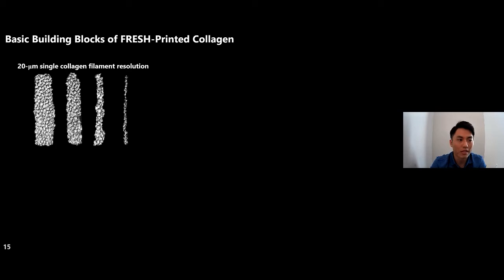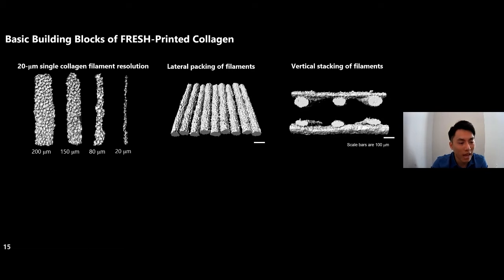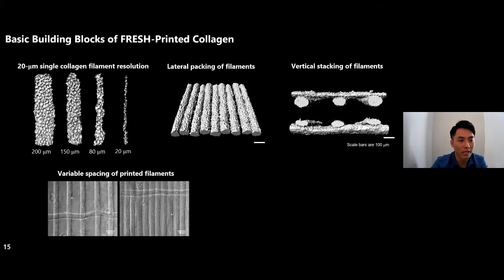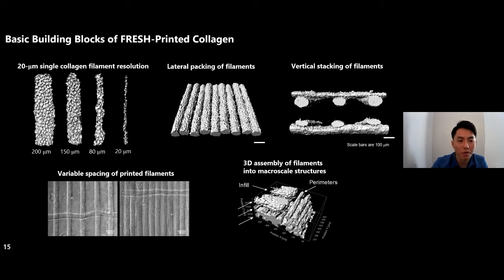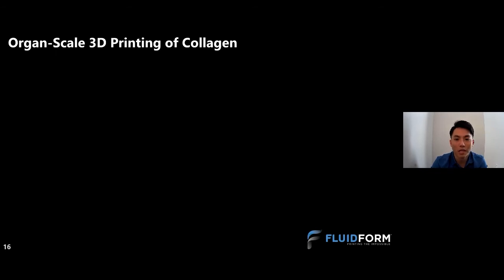So here we decided to print collagen type 1 filaments. So we went from 200 micron filaments all the way down to 20 micron filaments. And we're able to pack these laterally, stack them, and then very easily change the spacing between these printed filaments and start to assemble these filaments in 3-dimensional structures to produce these macro scale structures. And then leveraging these building blocks, we start to think about how this holds up in a larger print over multiple length scales, from the high resolution details to the organ scale structures that we might be interested in down the future.